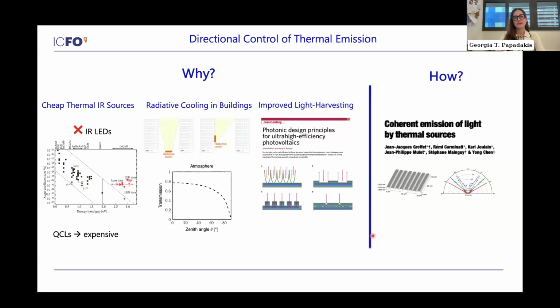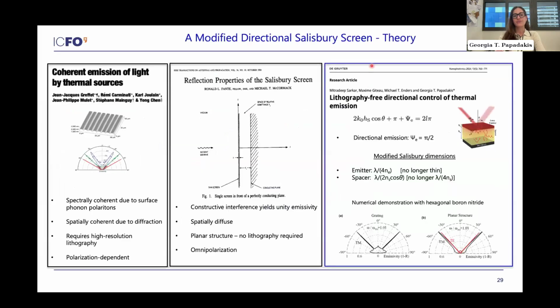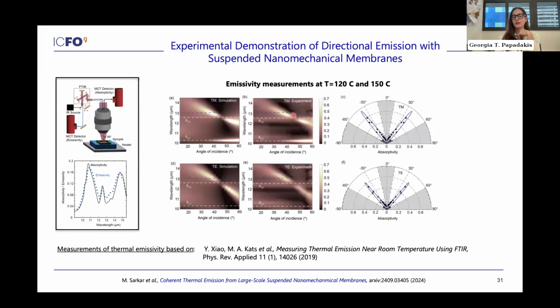Yeah, that's true. Hi Christos. For radiative cooling, for example, you need a broadband directional thermal emission. If you look at this paper here, where we derive the analytics of this, the key requirement is actually a high permittivity. The reason why this is narrowband in our case is not because the physics don't work otherwise. It's just because silicon carbide has a very high refractive index for a very narrow band frequency range. If you could find a material that has a very high refractive index for a broadband, or at least more broadband spectral range, then it would work.